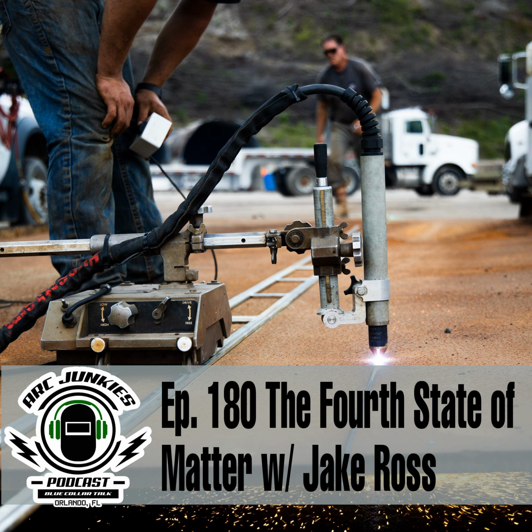So what's really unique about plasma arc gouging is we have a couple things. The first one is the reduction in noise. It makes less noise in comparison with a carbon arc gouging process. The other side is the metallurgical benefits, where you're not picking up additional material or adding carbon into your actual gouge. When you add that carbon in, you have to grind it out. You don't necessarily have to do that with the plasma arc gouging process.